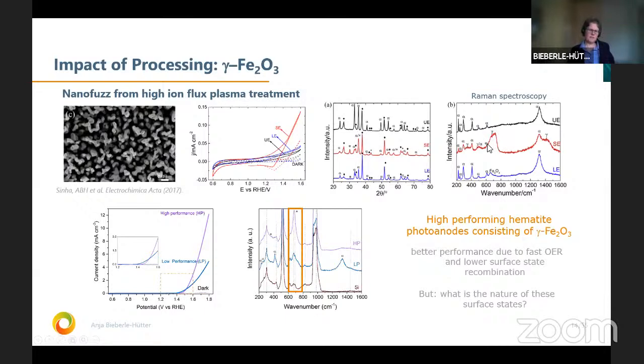And this gamma phase we also saw under certain conditions when we do sputtering. So the question is, but there we have to go further into more detail, can we stabilize a gamma phase and by this increase the performance? This is something which sounds interesting, and we would like to go into more detail. As I said here below, we have also found this gamma phase when we do certain processing with the sputtering. What we do not know yet is what is the nature of these surface states that we have there, because we have surface states, we have other surface states, but what is the nature there? So these are things which go further, but where we see that with such a simple material like iron oxide, there is still a lot of things we do not really know.